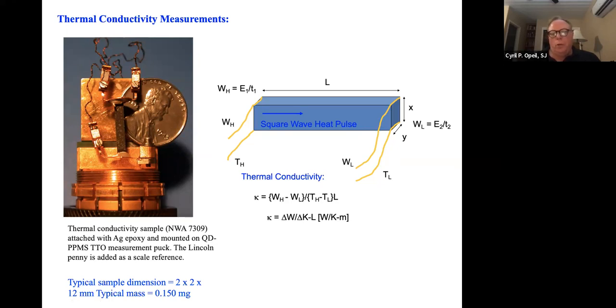Part of the reason, and I know this will fall painfully on the ears of some of the people who work with meteorites here, is that in order to do this technique, you need a uniform cross-section so that the square wave can go down through the sample. So unfortunately I have to cut the meteorites up into a particular geometric form. However, this is a highly reproducible technique, and it is used throughout work in thermoelectrics to determine thermal conductivity.